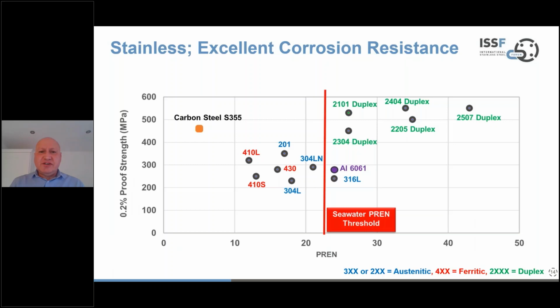Now, if we move on and consider corrosion resistance, and for people that have seen my presentations before, this is a standard chart that I use on a regular basis. And this chart compares proof strength versus the pitting resistance equivalent number, which is a way of measuring corrosion useful for chloride containing or marine environments. And you can see on here in the top left-hand side of this chart, carbon steel with its relatively high yield strength, but low corrosion resistance using this assessment method, which I would argue is pretty valid in a lot of situations. You have the vertical red line on the chart, which is the broad seawater threshold.